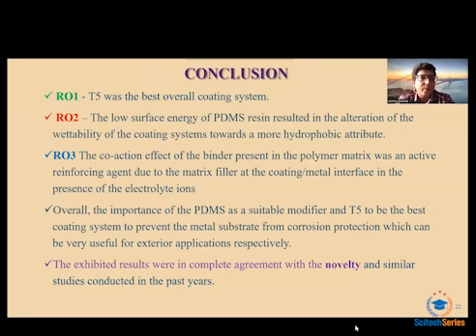And out of all the samples from T1 to T8, the T5 exhibited the best results, which contained 90% acrylic and 10% epoxy. The low surface energy of PDMS resulted in the alteration of the surface wettability of the coatings towards a more hydrophobic attribute. In this case, we also saw the results compared without the inclusion of PDMS and with the inclusion of PDMS. Therefore, PDMS is significantly vital to be added into the polymer matrix to enhance the surface wettability due to its hydrophobic nature and low surface energy.